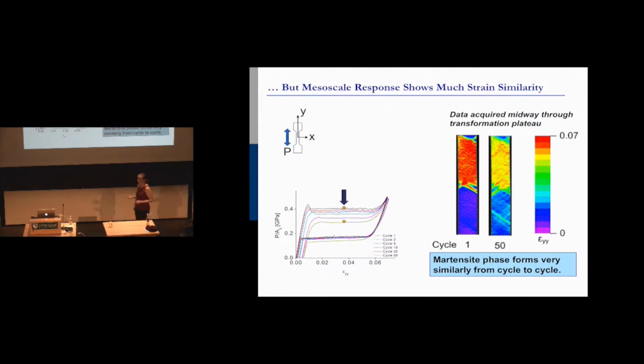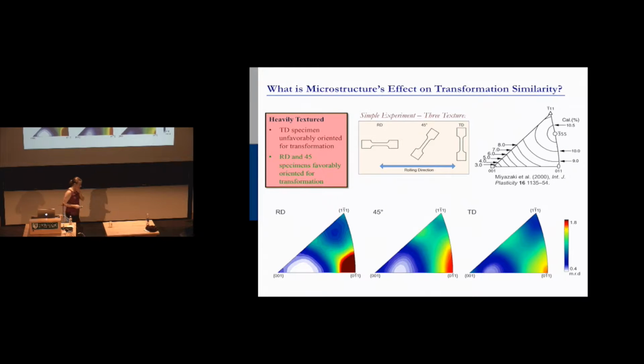This is important because it means that if you can control how the martensite forms on the first cycle, you can control how it's going to form on the 10,000th cycle if it's got a lot of similarity. So we wanted to quantify how much similarity there was. One of the first things we looked at, we did a pretty simple experiment. We wanted to see what microstructure's effect on this transformation similarity was. So we took a sheet and we just cut out specimens in 3 directions. We cut them out in the rolling direction, in the 45 direction, and in the transverse direction.